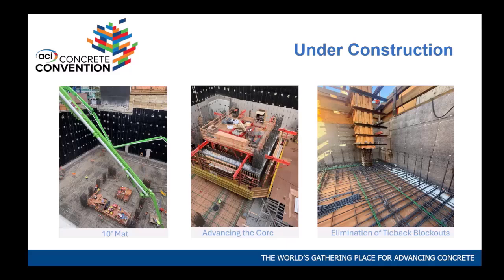Now, the underground, the below-grade construction was really interesting. First of all, we start with the mat. We had a lot of cool concrete specification for different concrete mixes for the building, but the mat is basically about 10 feet thick to plus 10. Around the elevator pit is about 15, but basically most of it is about 10 foot thick. And they did a single pour for the entire mat, about 5,000 yards. So basically, they start at night, they finish in the morning, about 12, 14-hour pour.